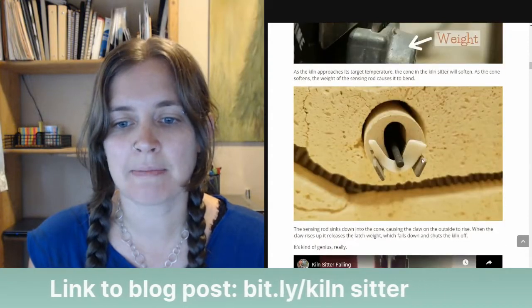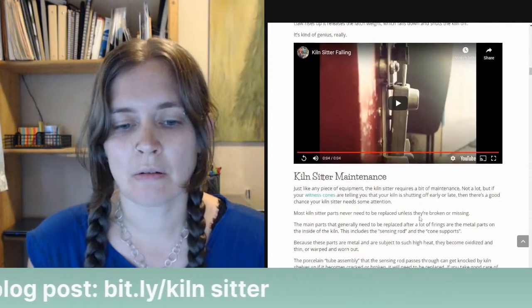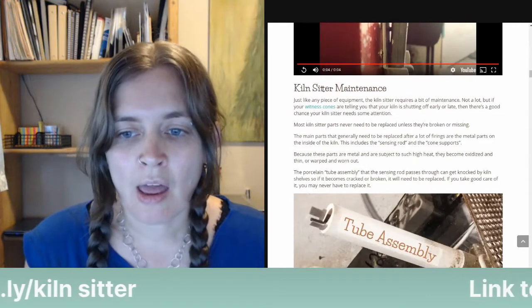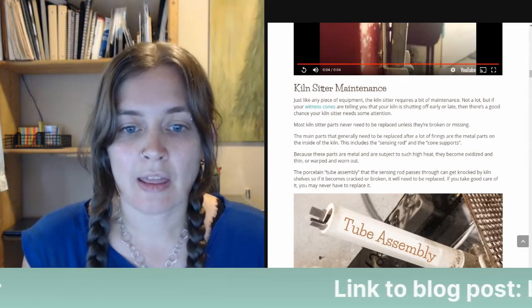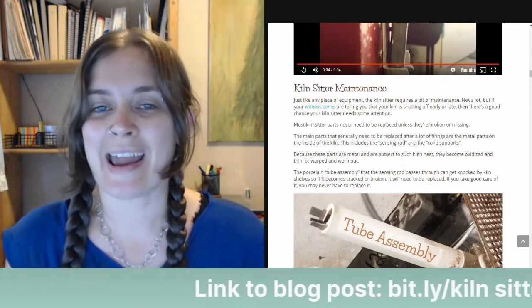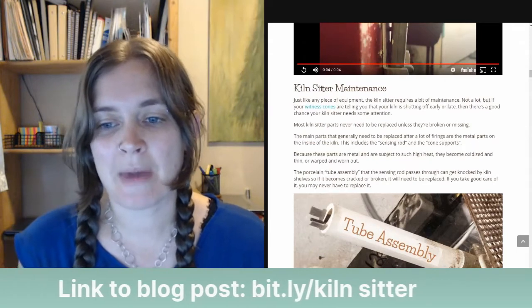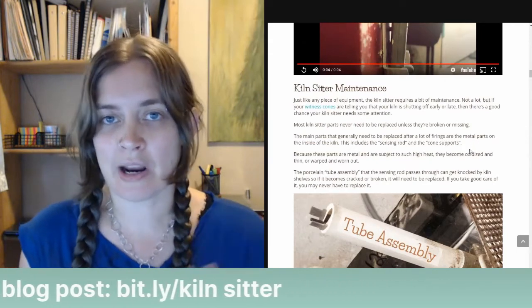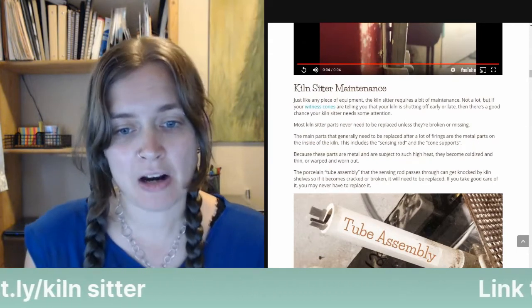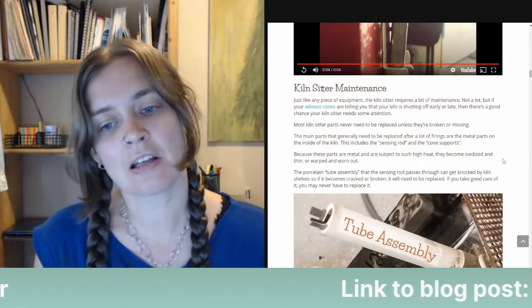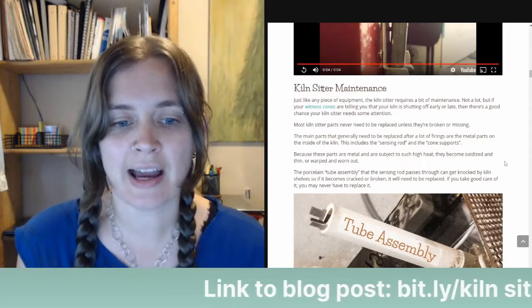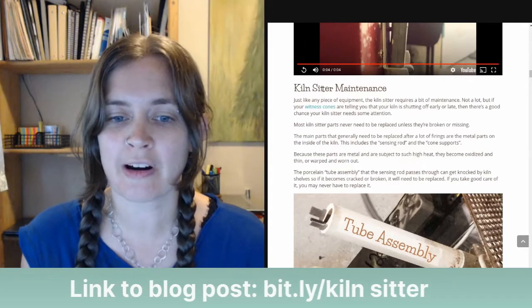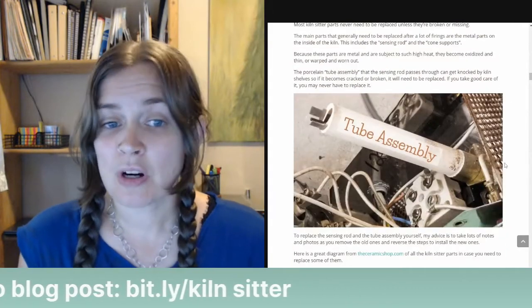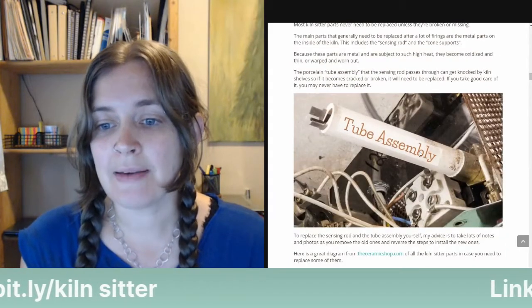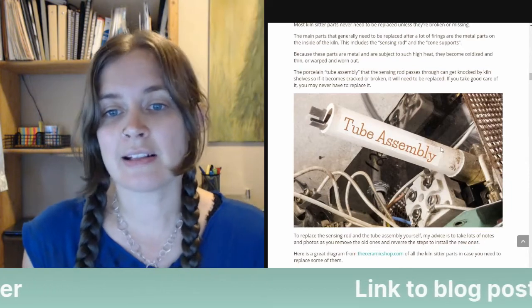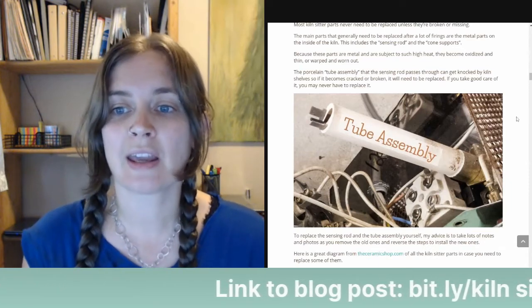Also these metal parts here. So this includes the sensing rod and the cone supports. So those are the metal parts that eventually wear down. Because these parts are metal and are subject to such high heat, they become oxidized and thin or warped and worn out. The porcelain tube assembly, as you see here, that the sensing rod passes through can get knocked by kiln shelves,